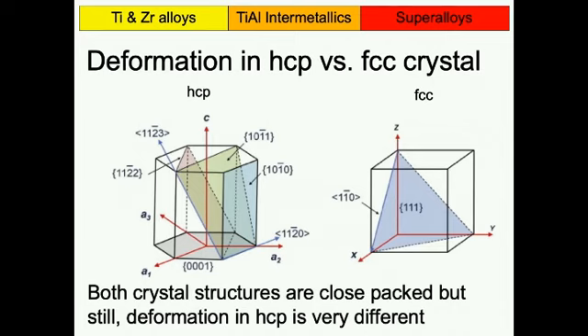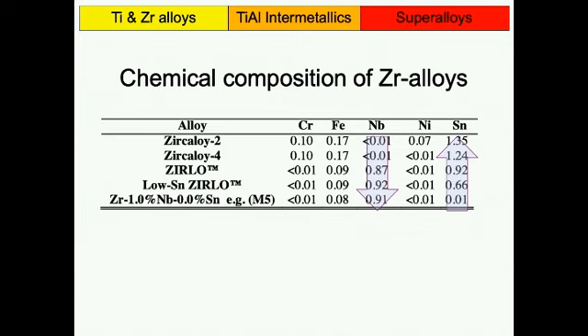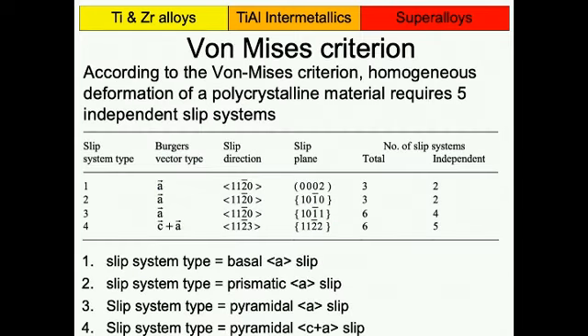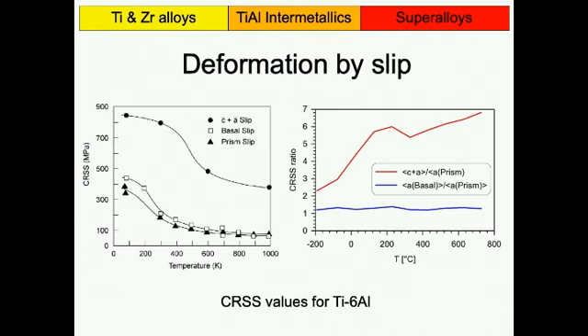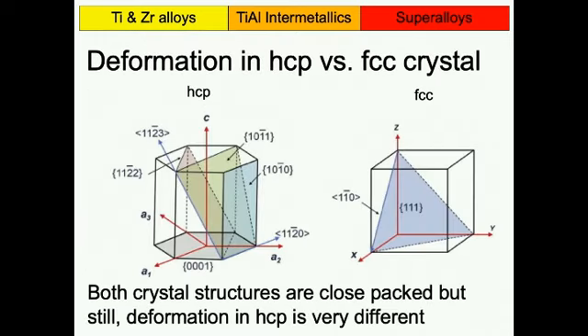The important point I would like to point out to you is the slip direction for these, the easy two here. They have the same slip direction, 1, 1 bar 2, 0. So it's shown here. You can see how this basal plane slips along this direction, or any of the variants of that. And the plane perpendicular to the basal plane slips in the same direction. That is, to some extent, the issue in HCP.